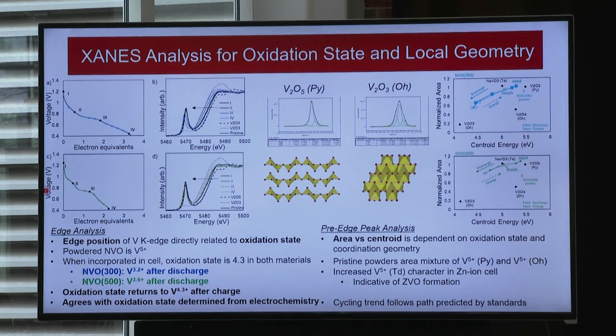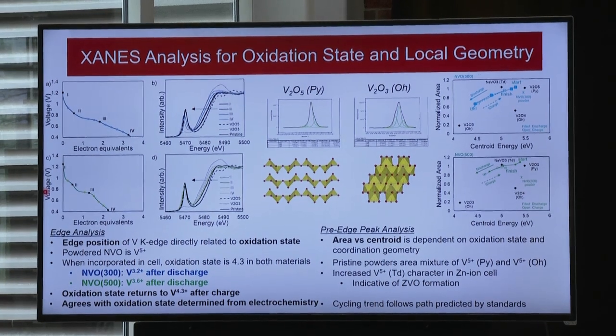We studied all materials using something called X-ray absorption spectroscopy. X-ray absorption spectroscopy allows us to determine the oxidation state of the materials, and these also were operando studies. So we can watch the evolution of the vanadium oxidation state as the battery is functioning. And in fact, vanadium changing oxidation state is the reaction that's taking place. So we're basically reducing vanadium as we discharge.